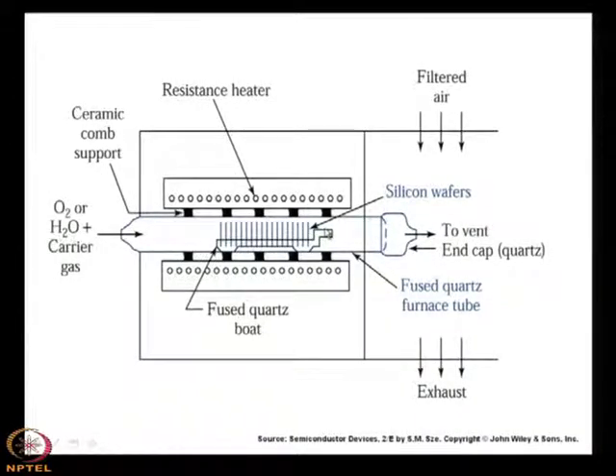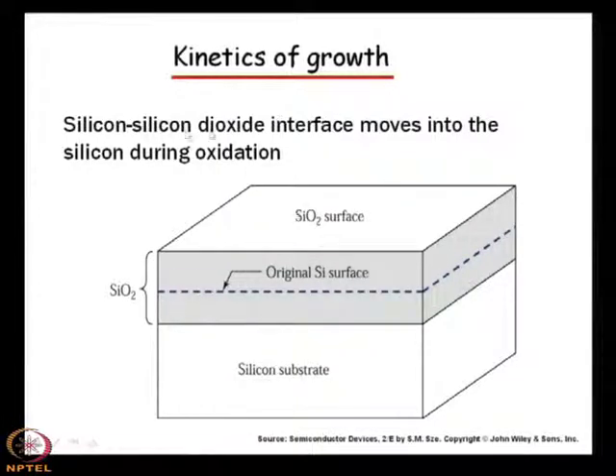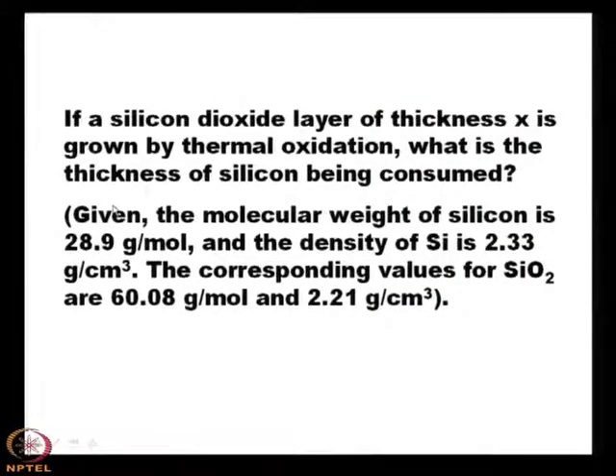So, till now what we have discussed is that the oxidation can be a dry one. You see that first there is a silicon-silicon dioxide interface, and it moves into silicon during oxidation. So, more and more silicon is consumed for the formation of SiO2. One example that you can try to solve: if a silicon dioxide layer of thickness x is grown by thermal oxidation, what is the thickness of silicon being consumed?